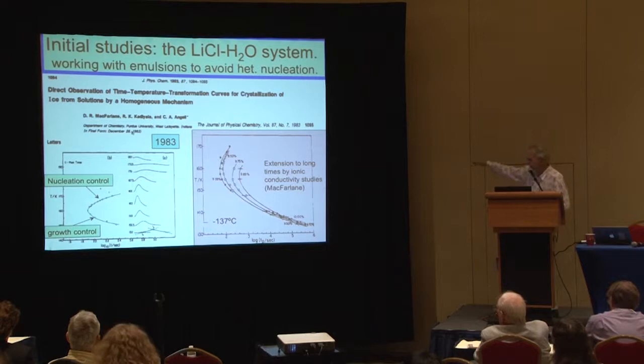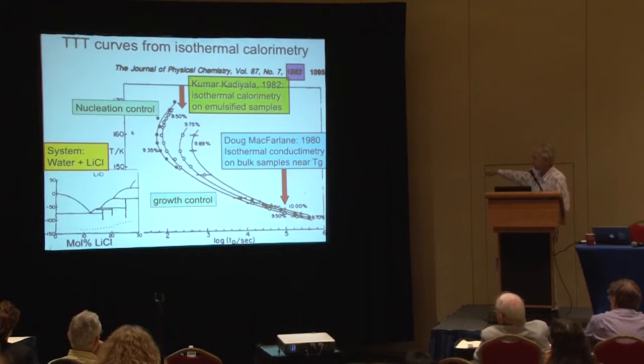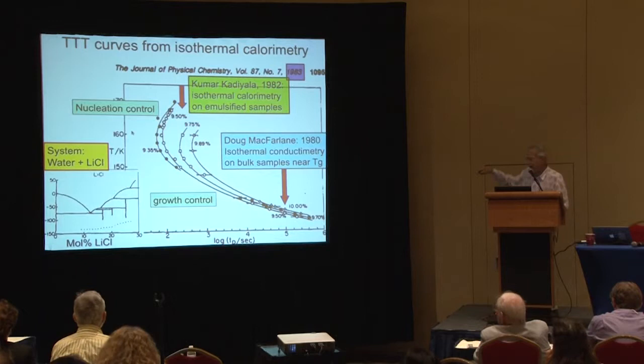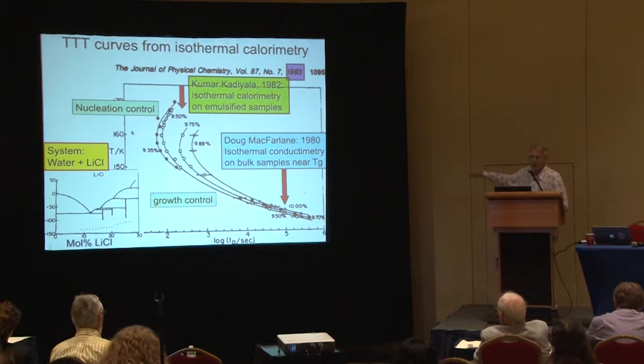Here's another one where we combined it with earlier work by Doug MacFarlane using electrical conductivity. Actually, this is on the next slide in more detail, where he extended this out to 10 to the fifth seconds, very, very long times, because conductivity is a wonderfully precise method. And we did a little calculation at the time, from the estimates of the diffusion coefficient, of how far the water molecules had to diffuse in order to crystallize at this temperature, which is very close to the water glass transition temperature. And it turned out to be a number we've heard quite a few times at this meeting, 2 nanometers. So here we're picking up almost the homogeneous nucleation event in this experiment.